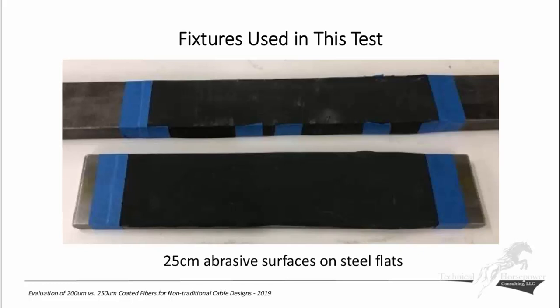Now, these are the actual fixtures we developed for this. These are basically steel plates. They're roughly 13 millimeters thick in order to give enough rigidity, and they're actually much longer than 25 centimeters in order to have a 25 centimeter paper on there. One of the difficulties was finding a way to adhere the paper to the bars, which had been machined flat, so that they did not cause a problem at the edge of where the tape sat. We didn't want to have extra compression at those points, which create high loss points. And this particular one shows a 50 micron paper on there.